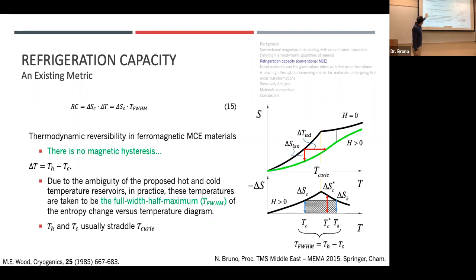The delta T they use for refrigeration capacity is a little ambiguous, full width half maximum. Usually the hot and cold temperature source of the thermodynamic cycle straddles the Curie point. And that's because you get the highest entropy change at the Curie point.